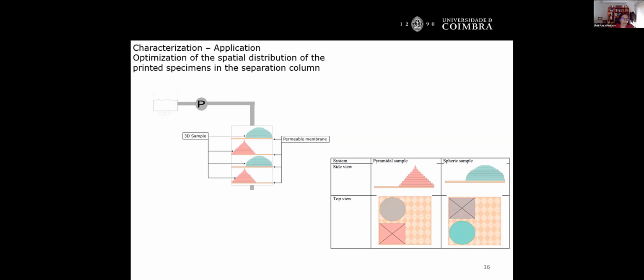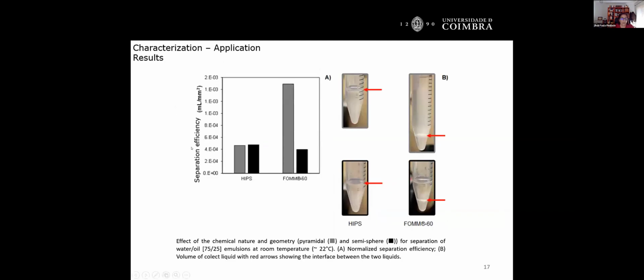So the results show us that the separation efficiency, considering the surface area of each one of them, was very, very similar for HIPS for both geometries, but very dissimilar for both geometrical shapes in foam. And you have a much higher separation efficiency for the pyramidal shape than for the semi-spherical shape.